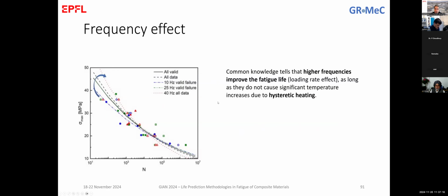There we also investigated the frequency effect. As we said before, the higher the frequency, the better it is, as long as you don't heat up. So here we did this. We've seen that even at 40 hertz, it's a very high frequency, it did not cause significant heating. Actually, it helped a bit. You see, with the frequency increase, we can shift the curve a bit to the right. So we can increase the performance a bit.